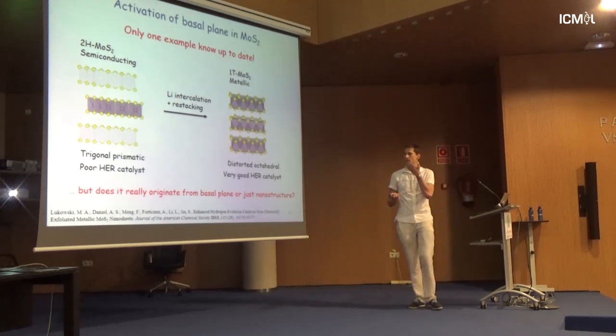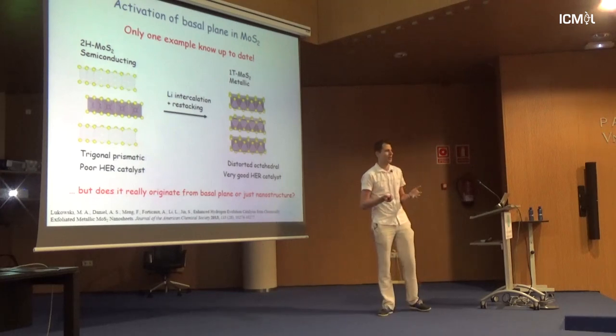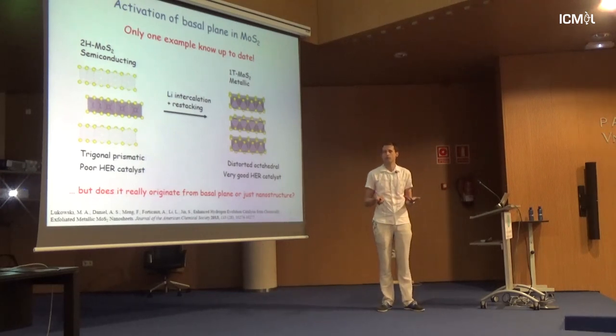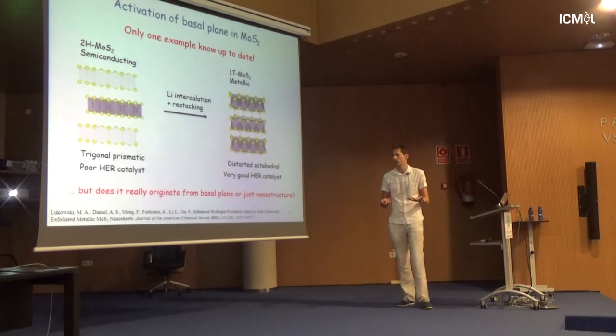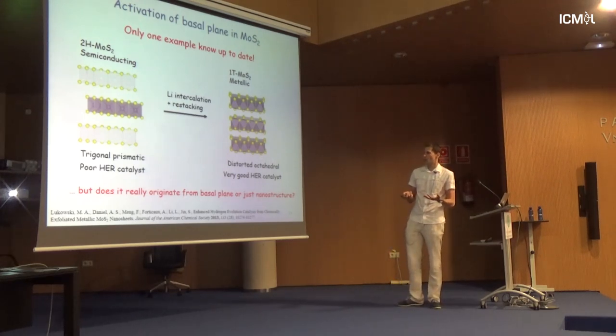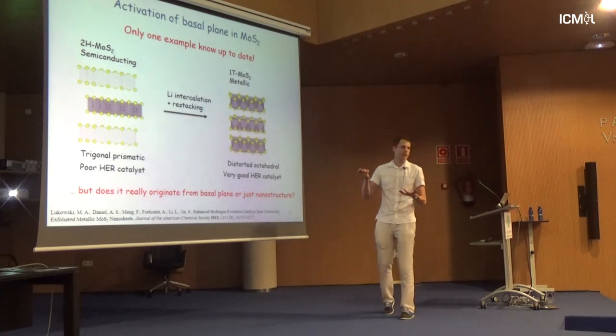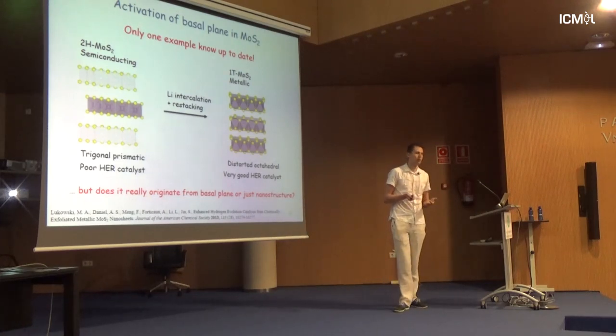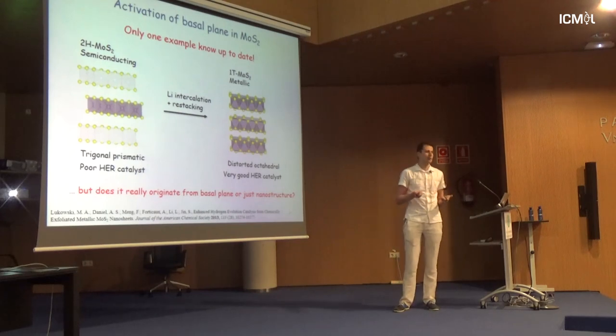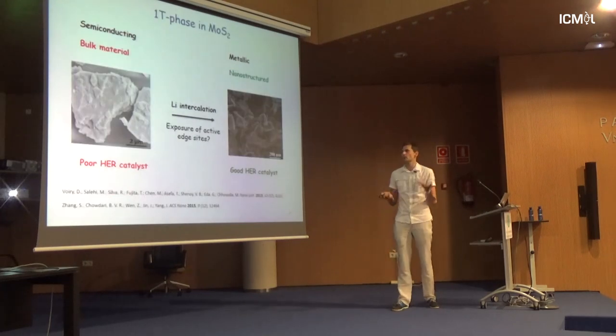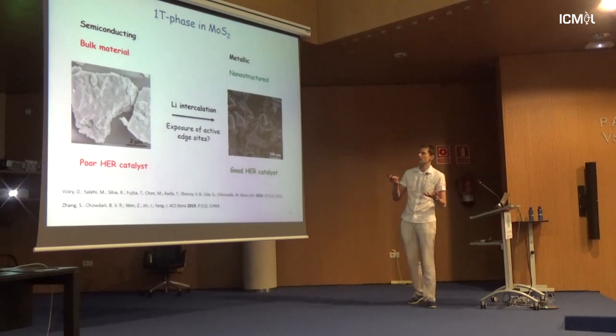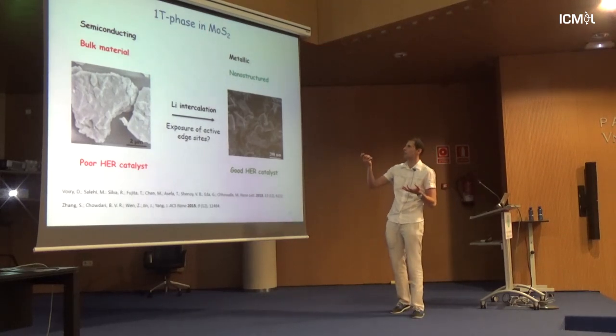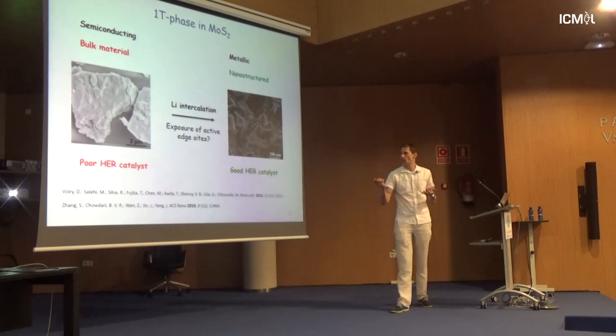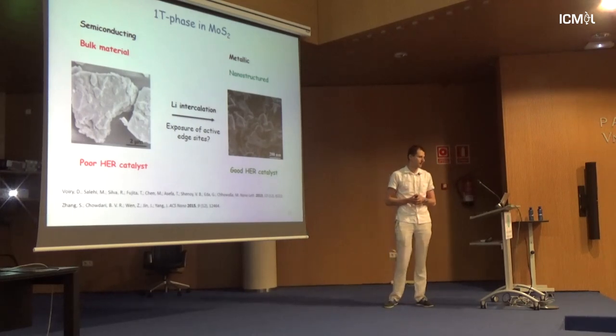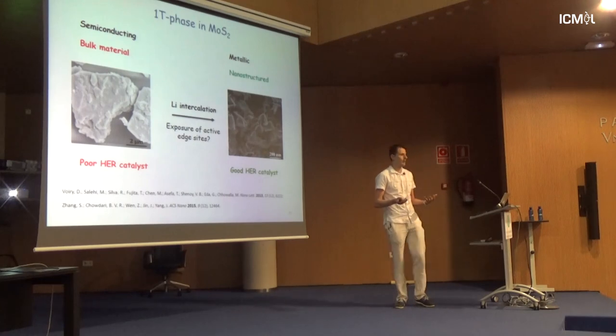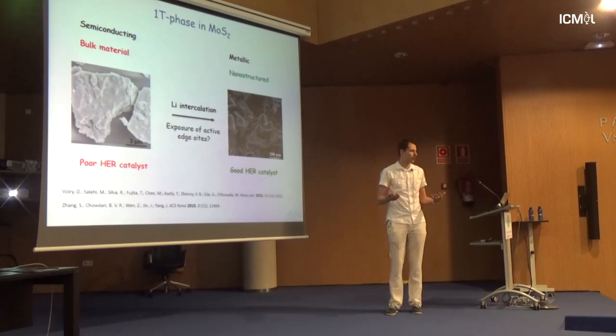But my biggest issue was not the chemical, not instrumentation, not morphology, because we're chemists and we do it all the time anyway. So once you intercalate lithium, you do a lot of damage to your material. So I was completely unconvinced whether the improvement was due to nanostructure or the improvement was through genuine switch of crystal structure.